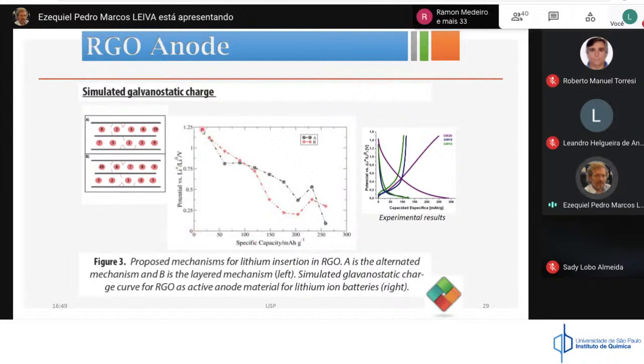You can see that when you have a small number of ions inserted, the insertion potential is relatively high. But as you put more and more lithium inside this material, the energy decreases, and finally you come very close to the lithium bulk deposition potential, which is here the zero. The potential here refers to bulk lithium ion.